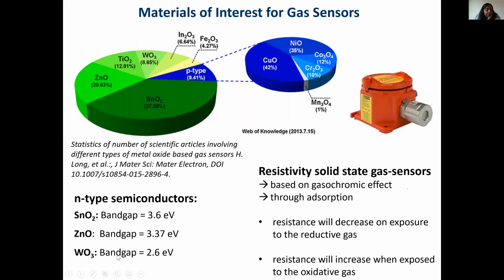And these materials have different band gaps. The highlight of these materials is that they always have oxygen-deficient surfaces, and that is quite interesting for gas sensing, because a solid gas sensor is based on the gasochromic effect. So you have adsorption of molecules, and the resistance could change. When you expose a material, for example one of the oxides here, the resistance will decrease upon exposure to reductive gases, or the resistance can increase when exposed to oxidative gases. And this is where you select the materials of choice for which gas sensing.